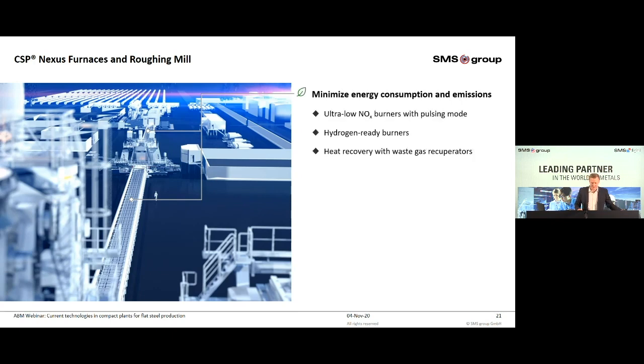The furnaces are designed for minimum energy consumption and emissions. Ultra-low NOx burners are used in the pulsing mode to always run in the most efficient working range. These burners are hydrogen ready and can be operated with gas, hydrogen mixture, or even 100% hydrogen. The heat of the waste gas is used to preheat the fresh air by recuperators.